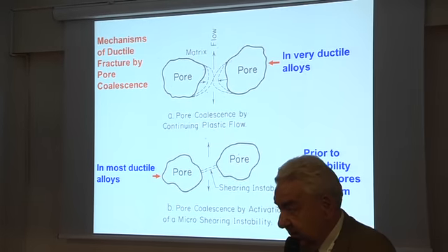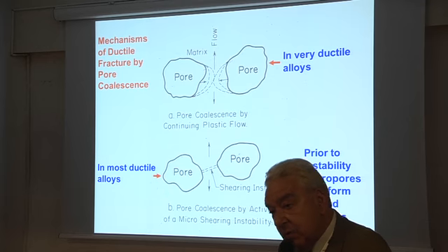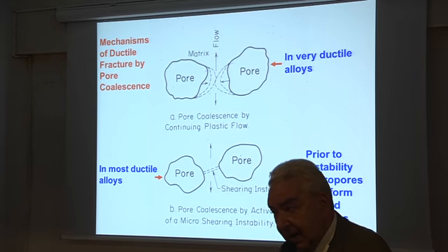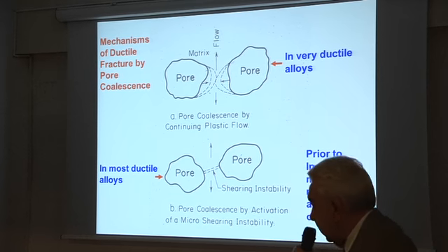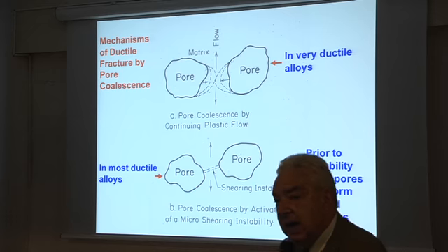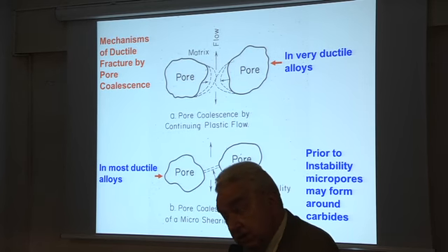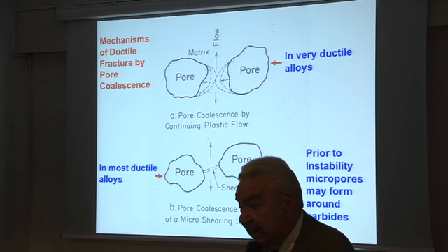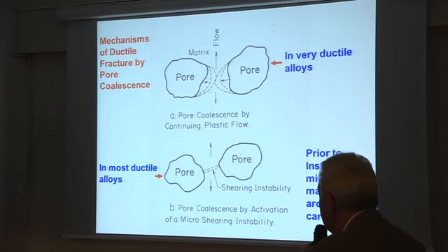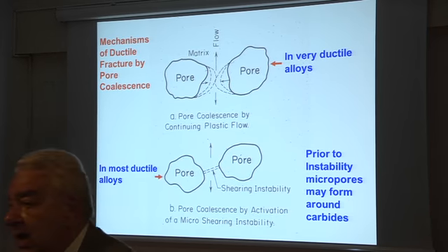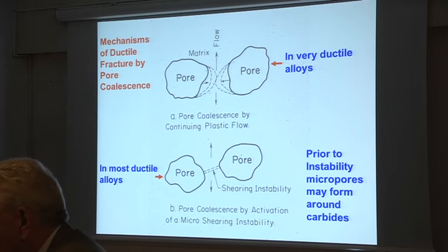What's a shearing instability? It's a mode 2 fracture, because the two sides around this shearing instability behave as rigid bodies sliding one against the other, like in here there was a tiny veil of lubricating liquid.